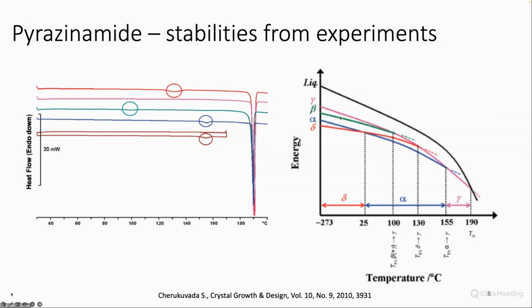Of course, we don't know the exact thermodynamic transition points. These different phase transitions may be kinetically hindered, and so there's still something that isn't known, but at least there's something that points to the alpha form and the gamma form being the most stable forms at higher temperatures. We can see that the free energy curves here are a bit steeper than the curves of the beta and the alpha form, beta and delta forms.